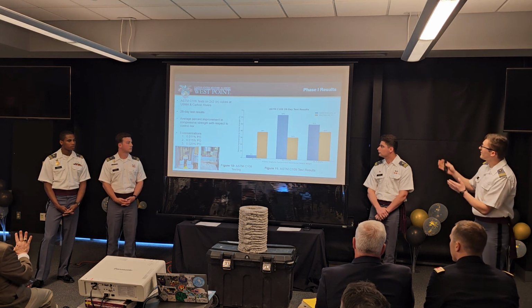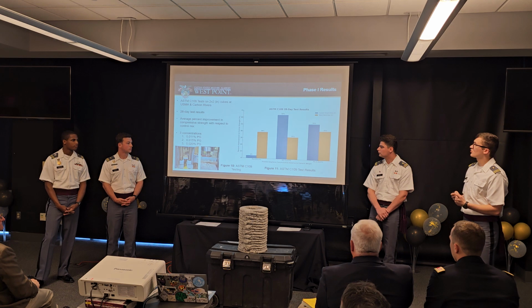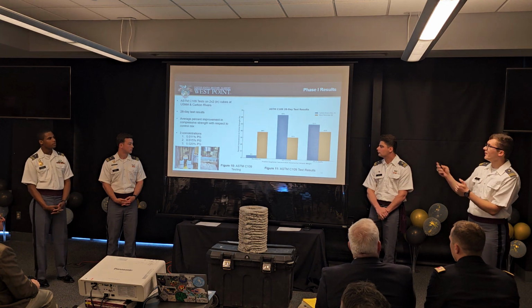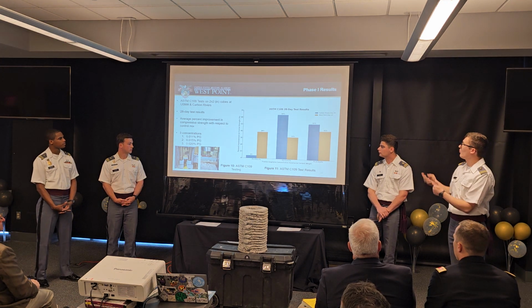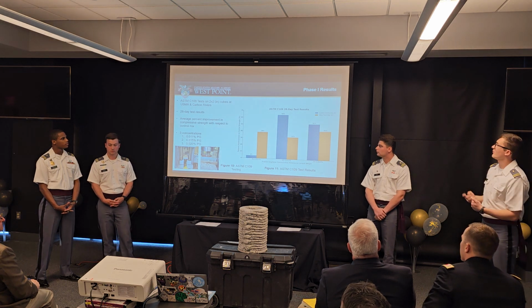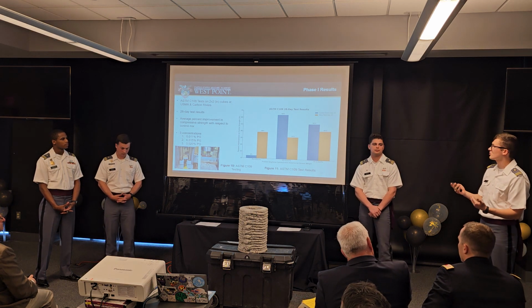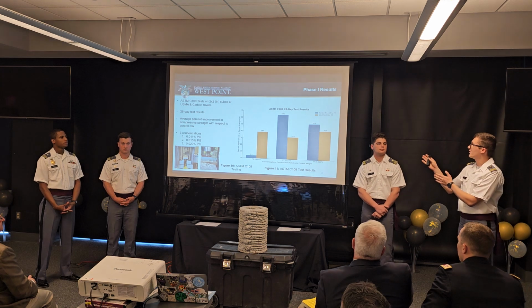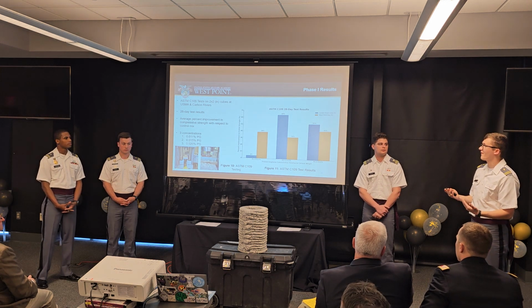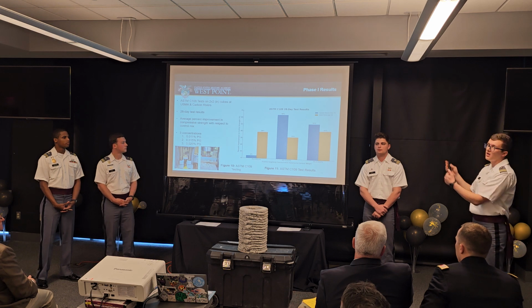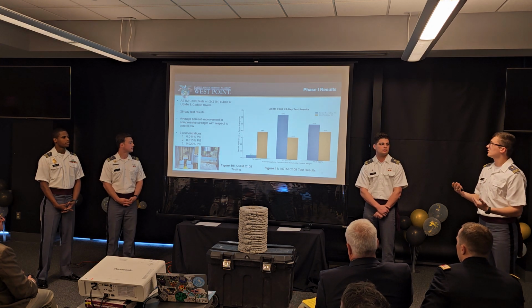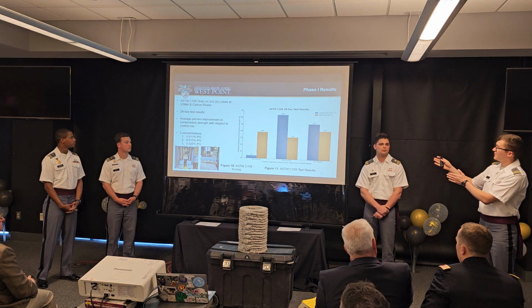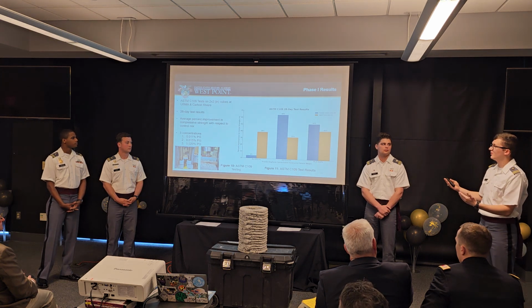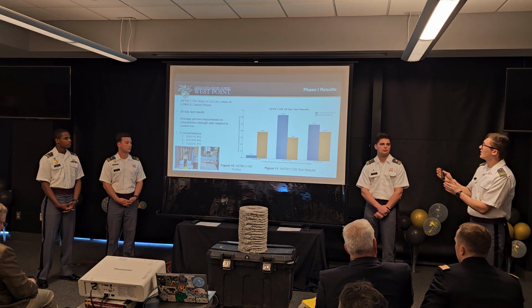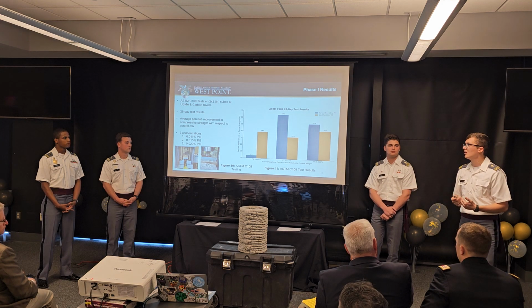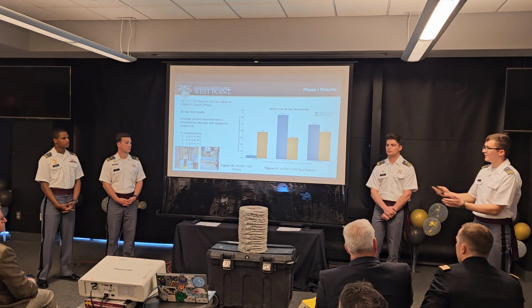which will result in a 51% improvement in compressive strength with respect to the control mix, while we have a 64% improvement, also with respect to the control mix, in compressive strength of the concrete mix for 0.015% of crystalline graphene concentration. At the end of the day, during phase one, we decided to conclude that this 0.015% concentration would be the most optimal mix that we would proceed with during phase two of our concept of operation to 3D printed concrete culvert that you can see.